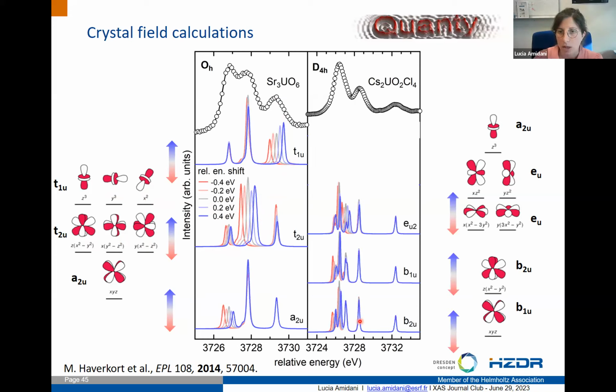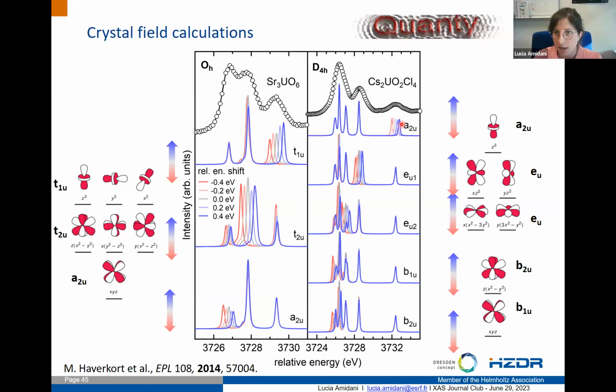Similarly, if we go to the uranyl, the first three groups of orbitals which we try to tune are all giving effects that can be concentrated below the first peak. And then the second EU group was affecting this peak that is below peak B. And then, as you can guess, the A2U was moving here. So this was a nice confirmation from the crystal field approach of the interpretation that we gave with DFT.